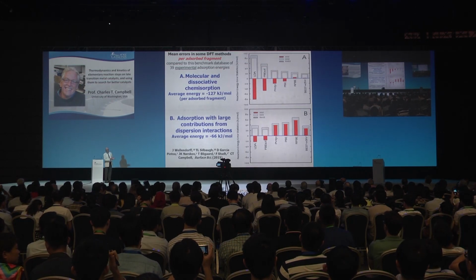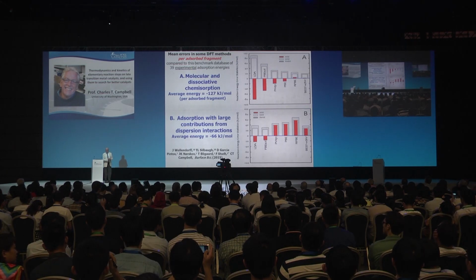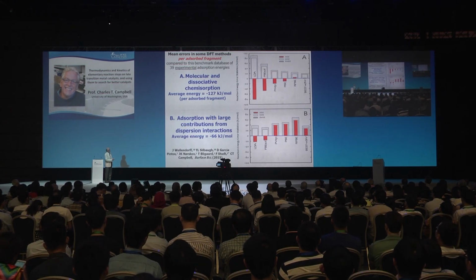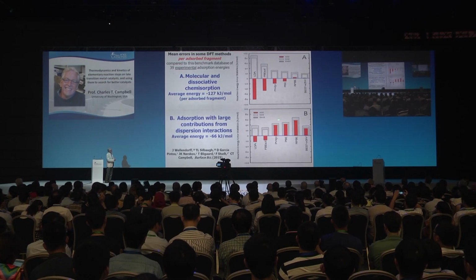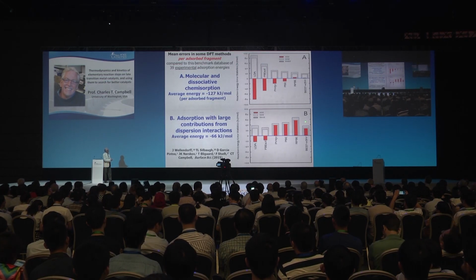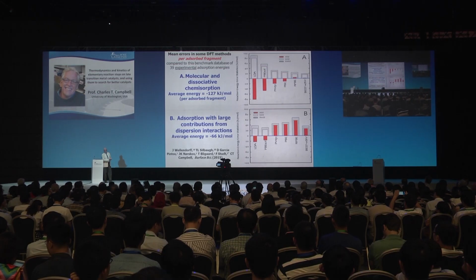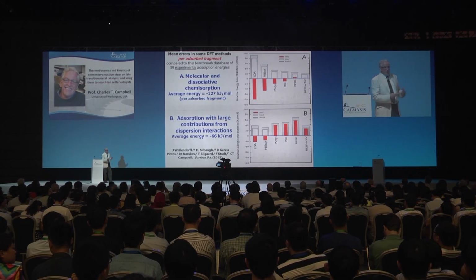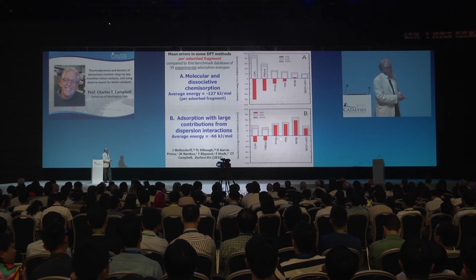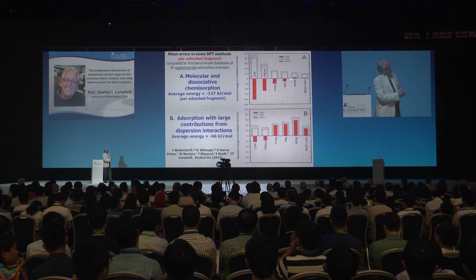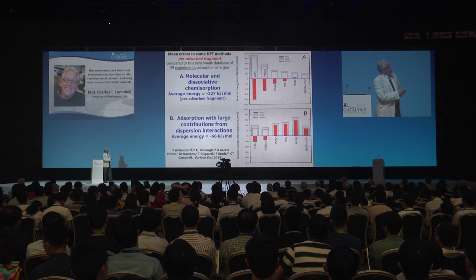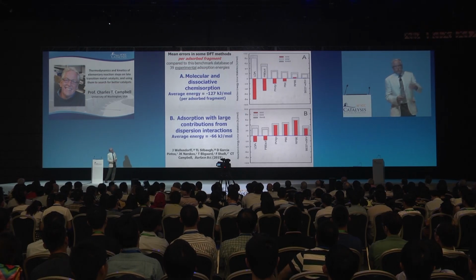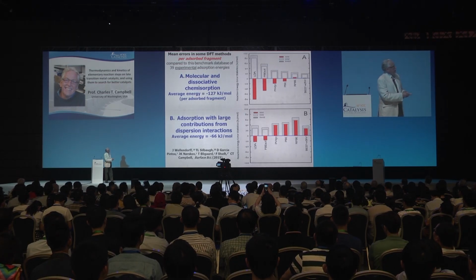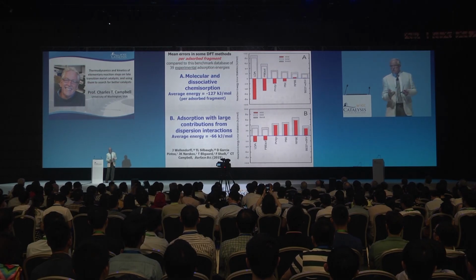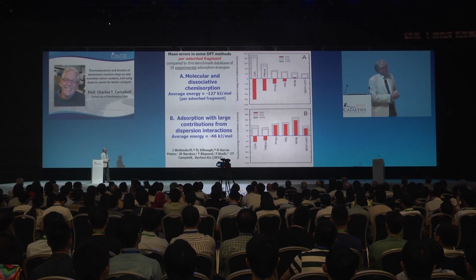These are for pure chemisorption systems, small molecules like CO, oxygen, small adsorbates, hydrogen atoms, NO. And these are the subset of that group of reactions, experimental reactions that have large contributions from van der Waals interactions. And the red errors are kind of not interesting. They're signed errors, so the negative errors cancel with the positive errors. Look at the other error bars that are in the other two levels here. They're pretty big errors, actually, in state-of-the-art density functional theory for adsorbed species.